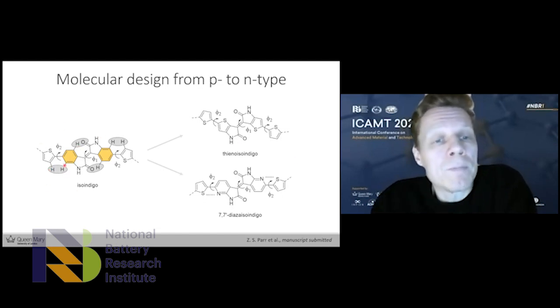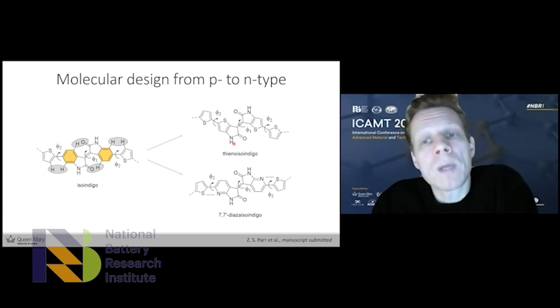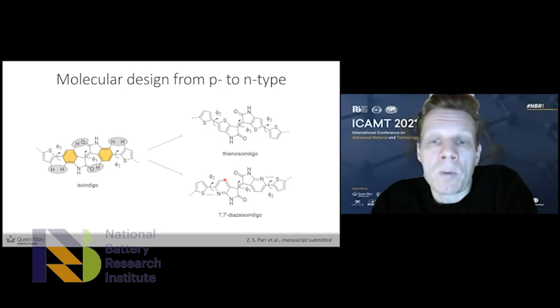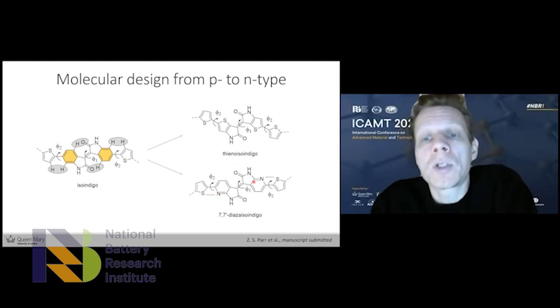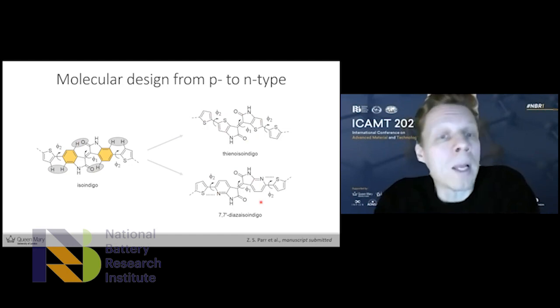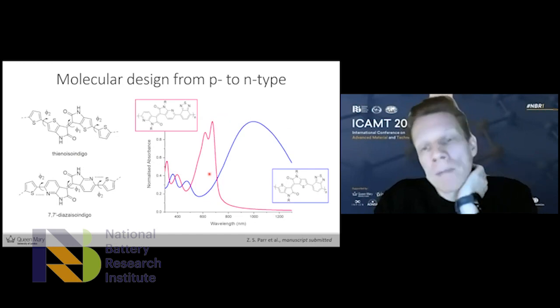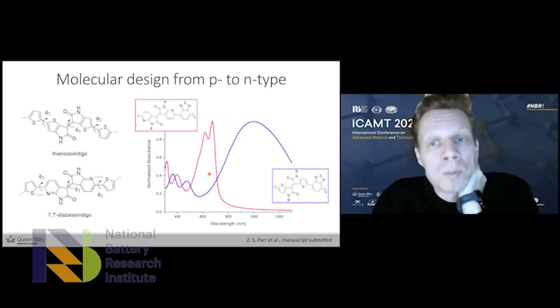There's lots of steric hindrance in this system, indicated here by the gray curved ellipsoids. So we've done some structural modifications to get a more planar polymer backbone. One is the thieno isoindigo shown here, and the other one is the aza isoindigo, where we've substituted one of the carbons with a nitrogen. In both cases, you get much more planar polymer backbones. And these two systems have dramatically different optical properties.